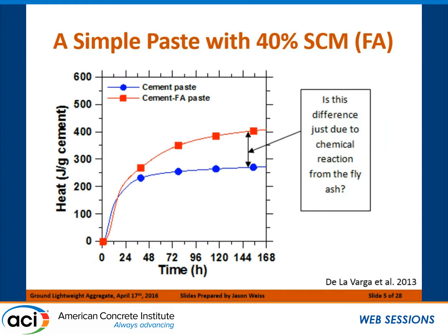Now, this is a plot that comes from Igor de la Varga, and he's in the room hiding out behind a beard back in this area here. This was some work he did looking at high volume fly ashes, where we used a lot of fly ash to replace cement. If you looked at this, you would say, here's the heat released per gram of cement, so this whole difference here must be the reaction of the fly ash itself. That's essentially the pozzolanic reaction kicking in, and it's this huge amount.